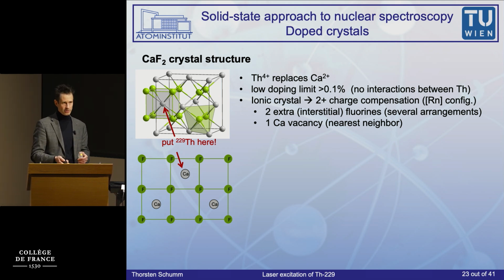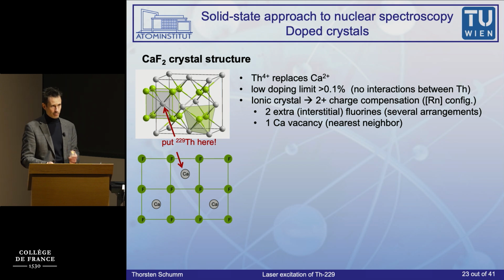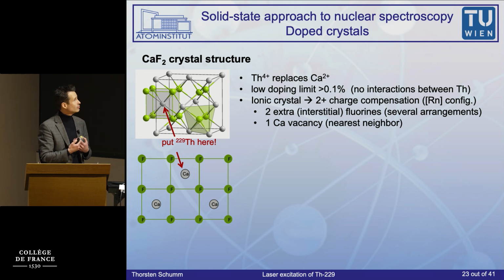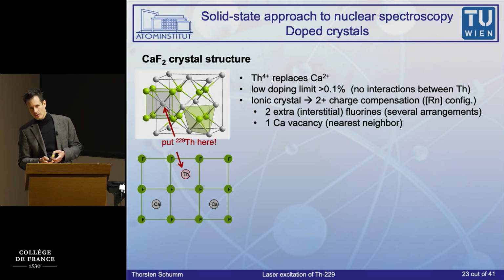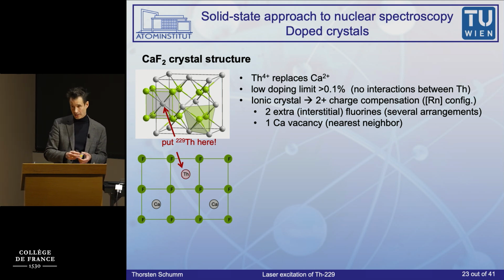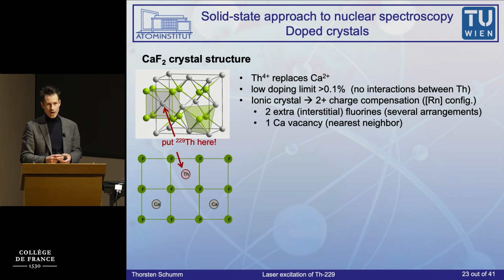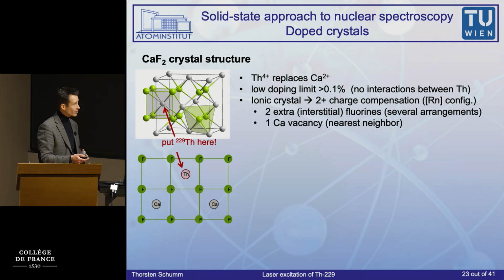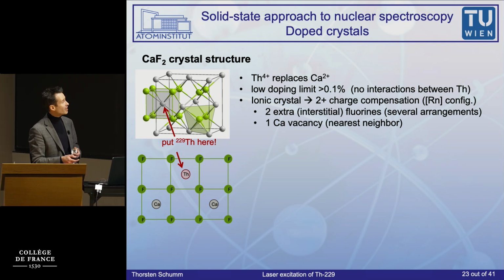Not in a chemical way, but really by melting a crystal. So this is the calcium fluoride structure. Luckily for me, who is really not strong in solid-state physics, it's a very simple cubic lattice structure. And so every now and then we replace a calcium with a thorium. We put a thorium where the calcium sits. I will show you in a slide how we do that. So it doesn't really change a lot in the crystal structure, since they have similar ionic radius.